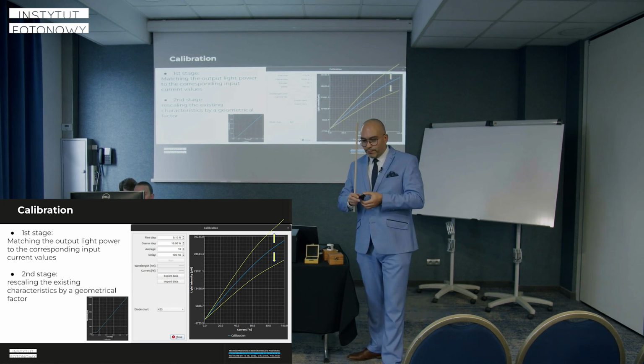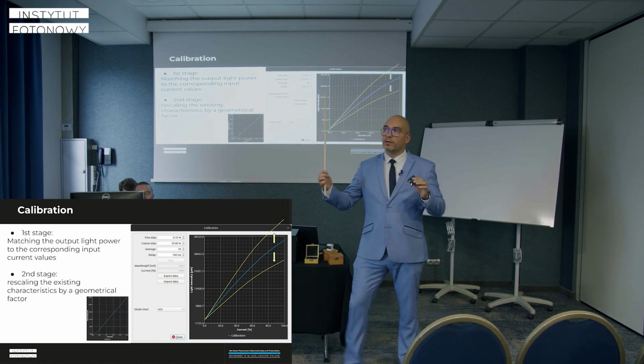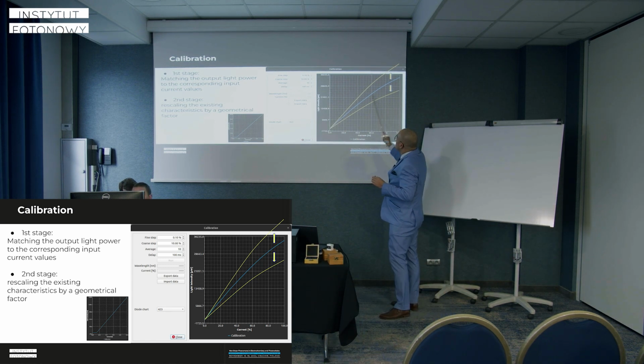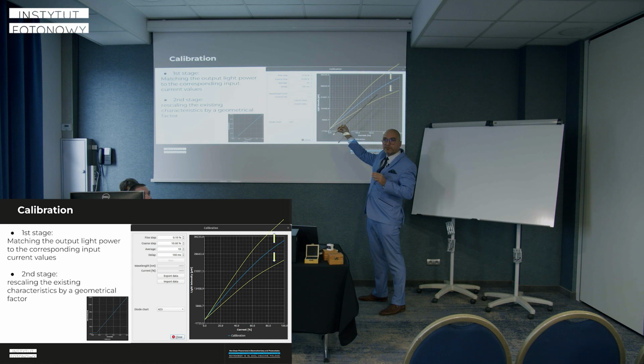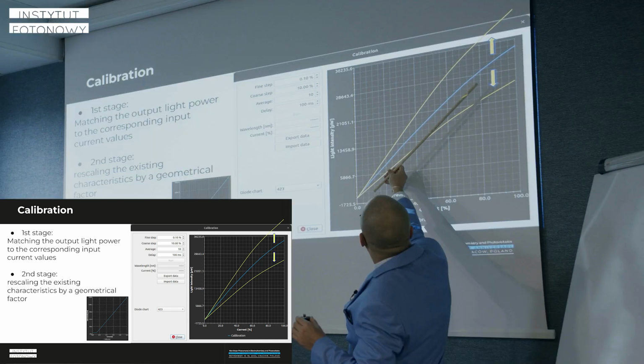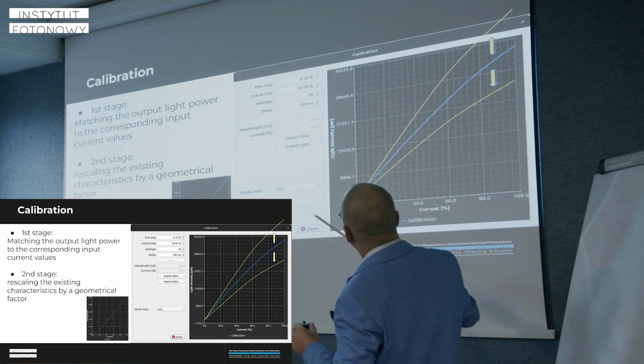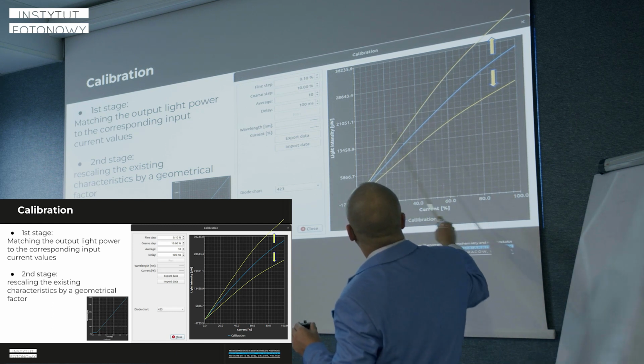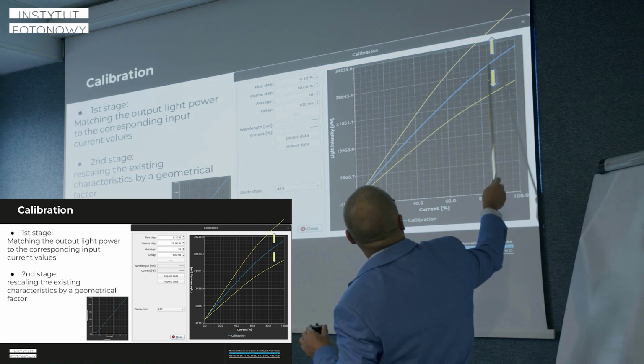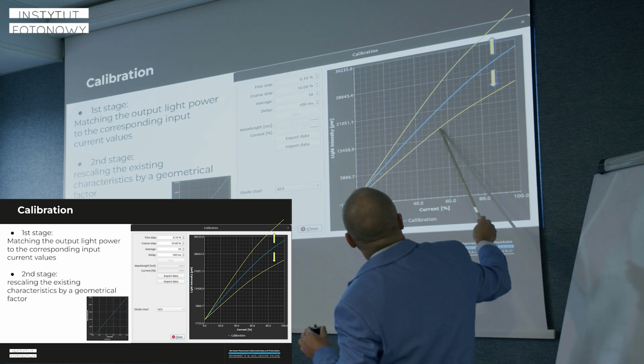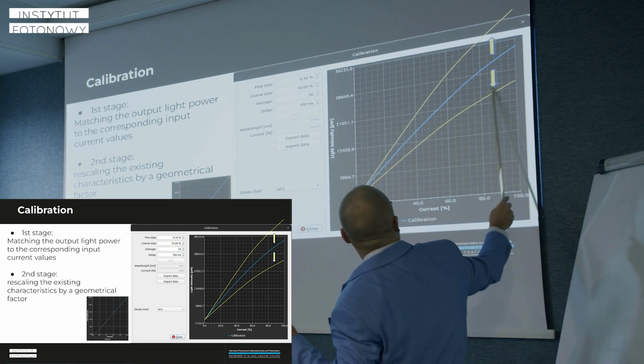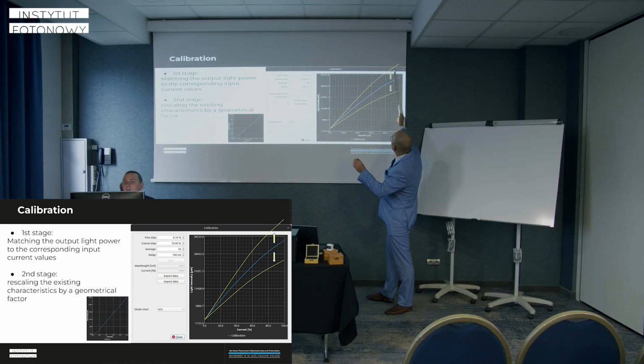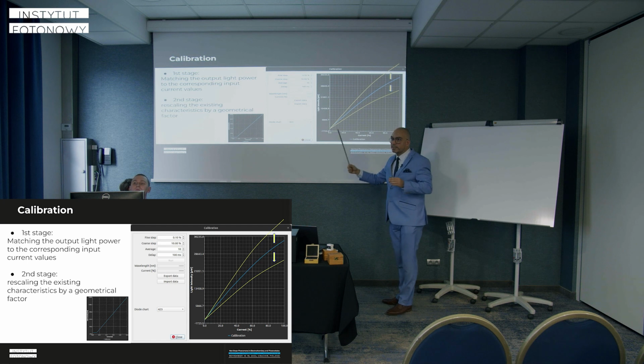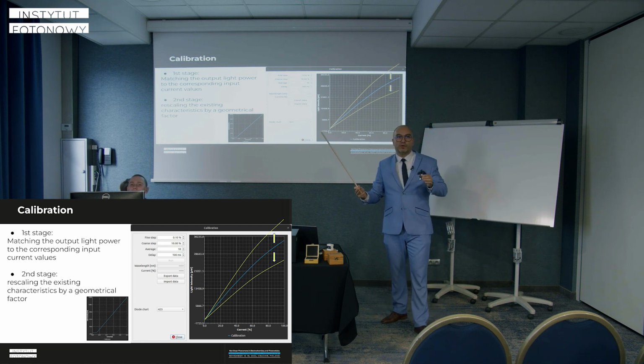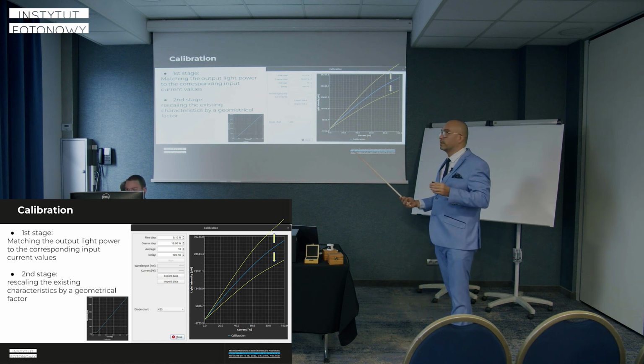So if we move farther from the light source, we don't have to perform all the calibration once again, which is quite long. We just perform another step, which is geometrical calibration, and only the slope changes. It is enough to do it for each diode at, for example, 50%, and then we rescale this curve. When we move farther, the intensity is a little bit less, or closer, a little bit more, and then we just rescale this curve by a factor of 0.9, for example, or 1.1.